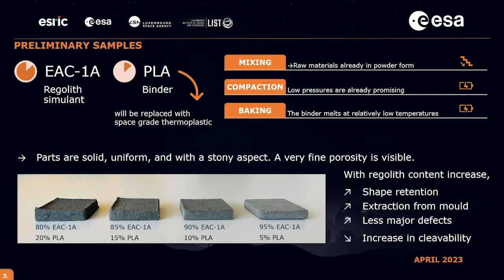So we mix in powder form and in dry form regolith within a thermoplastic binder. We compact those powders with a low pressure, and we bake them so that the binder melts. We knew that this might have worked because we already had some experience on that. Last year, in the same conference, a colleague of ours presented the idea of mixing the EAC-1A, the regolith simulant we are using, together with PLA to get a filament for 3D printing.